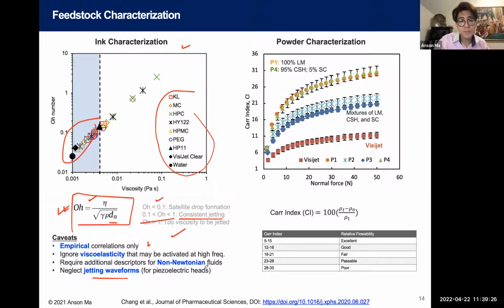and jetting experiments. But it doesn't account for things like elasticity, which could be important as a rheologist. That could be very important at high frequency, but it's ignoring that. And it's also not directly dealing with the fact that some of these inks are non-Newtonian fluids, meaning that the viscosity is a function of shear rate as well. But nevertheless, you can do some of this as a first screening of materials.